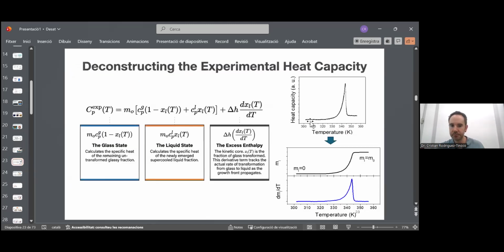vitrification process. And what you see here is a typical calorimetric trace. This is the glass. We enter the vitrification window, let's say. This is the onset of the vitrification. We have this jump, which is due to the excess of enthalpy. And then once it is transformed, we measure the heat capacity of the liquid. Glass, liquid, and transformation. This heat capacity can be modeled with this equation.